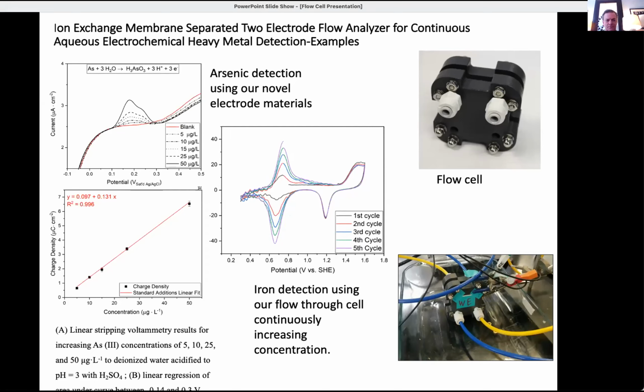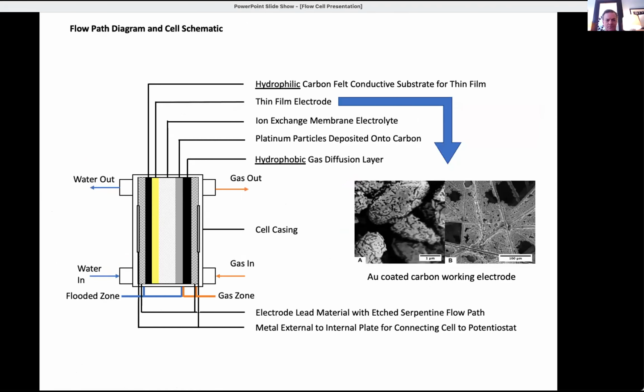There's a number of things which make this cell novel compared to some of the past techniques, besides being able to be used continuously. So in this cell, we've developed a very low-cost gold-coated carbon working electrode. And by gold coating, we're literally talking about a layer of less than 10 nanometers of gold on the carbon surface. So the loading is micrograms of gold. So it's insignificant, the amount of gold here, as opposed to systems which use gold wires and gold foils, or printed gold thick film layers, which cost hundreds of dollars for a single electrode.